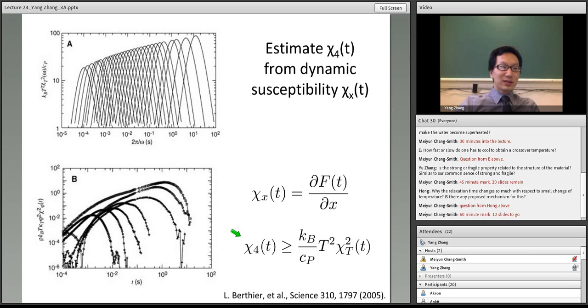In this slide, let me show you the estimated 4-point correlation function from experiments. The first one, A, is chi T, which is basically the temperature derivative of the intermediate scattering function. The second one is chi phi, with respect to volume fraction. This approach is very significant because it gives us a way to estimate the 4-point correlation function. Although it's not a direct probe, we can already estimate the lower bound.